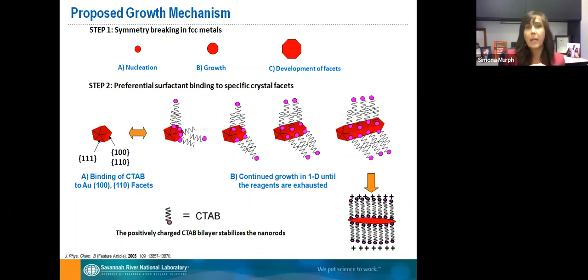If we take a step back and try to come up with a growth mechanism, we are trying to see how exactly this grows. We start with the nucleation, and as we form more gold atoms, you start to develop these facets. In the presence of cetyltrimethylammonium bromide, you can see that we have different binding on the surface, and you start to grow these one-dimensional nanostructures. This CTAB is acting as a bilayer on the surface. The hydrophobic functionality interdigitates on the surface, and the other end binds on the gold nanoparticle surface.